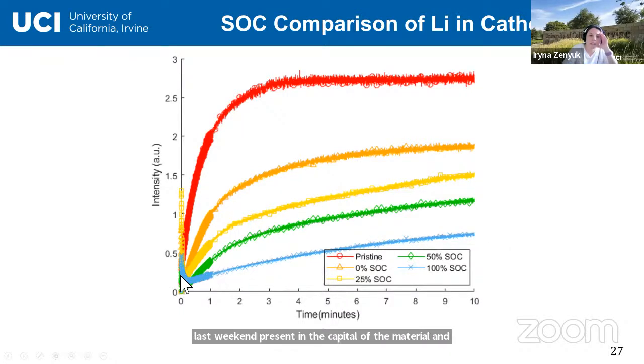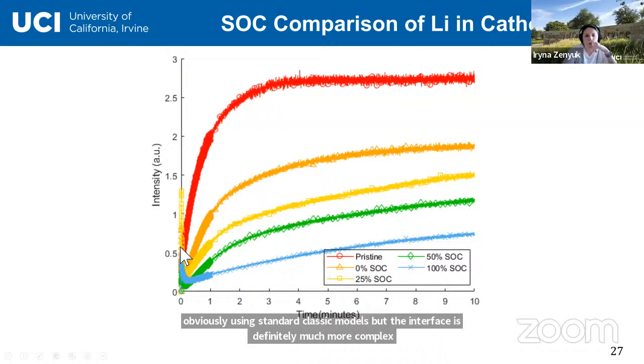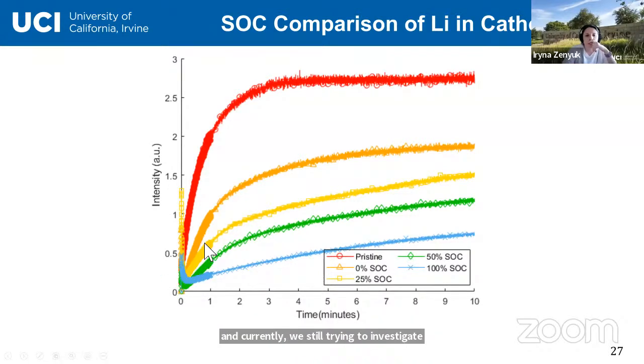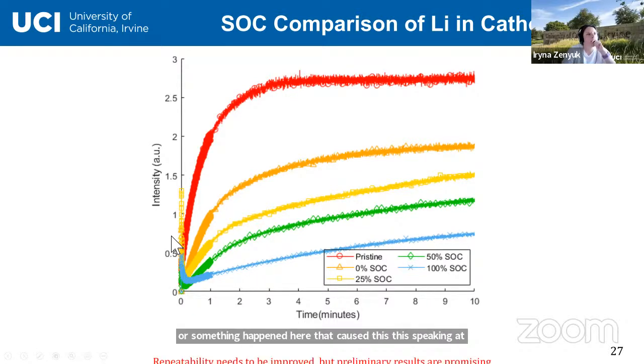And it's interesting, the dynamics change too at the interface. I think the most interesting part is zooming into this area here to show how the lithium concentration changes at the interface, because in bulk we can predict using standard classic models, but the interface is definitely much more complex, and currently we're still trying to investigate this behavior, this peaking at the interface, and whether maybe there was some lithium plating or something that happened here that caused this peaking at the interface.